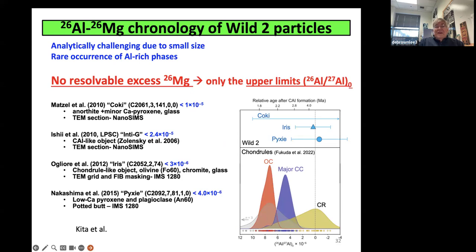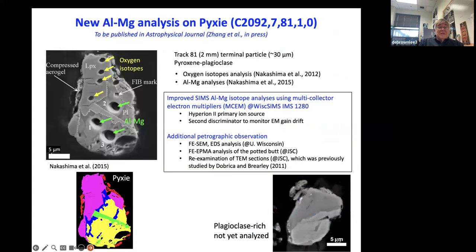So an exciting part of the analysis has been the data that's been able to be obtained from aluminum-26, magnesium-26 chronology. This is very, very difficult because the particles are small and because there aren't many large regions that have a high aluminum-magnesium ratio. Nonetheless, a variety of particles have been analyzed, and there's been no resolvable excess magnesium-26. So all we've been able to do is set upper limits on the initial aluminum-26-27 ratio, and we'll go through this.